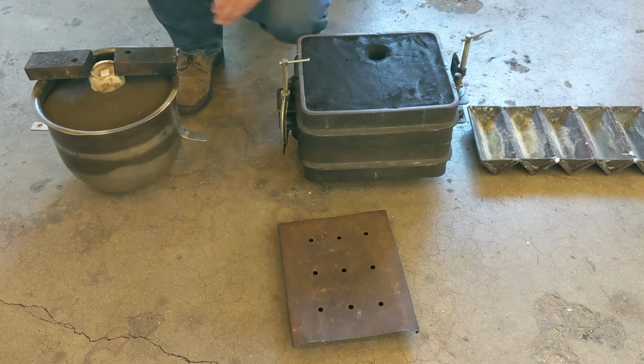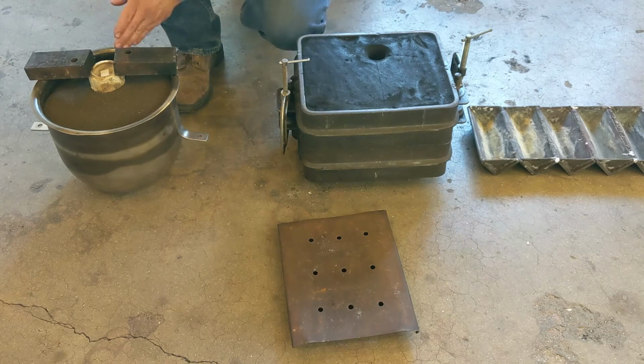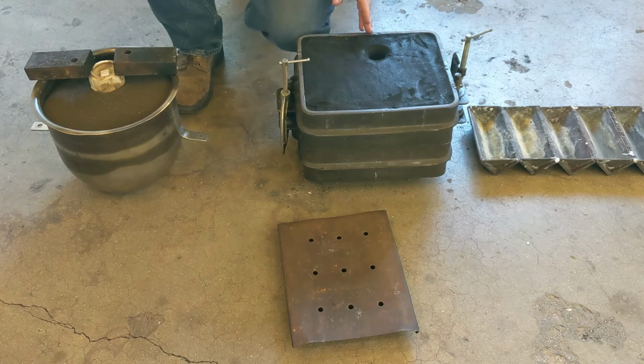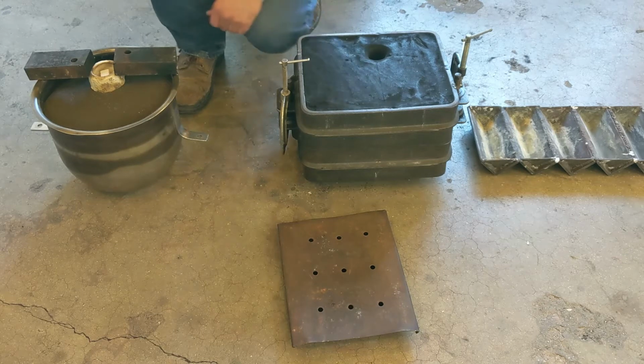So the order of the pour is going to be the lost foam mold at 1450. Remember, we needed that extra temperature to vaporize the polystyrene foam pattern. Then we'll move on to the green sand mold. By then, the metal will probably have cooled off a little bit to 1400 degrees Fahrenheit or just below. And then once we've filled this mold, we'll pour off the excess. After we give it 20 or 30 minutes for things to cool and solidify, we'll unmold and remove our castings.